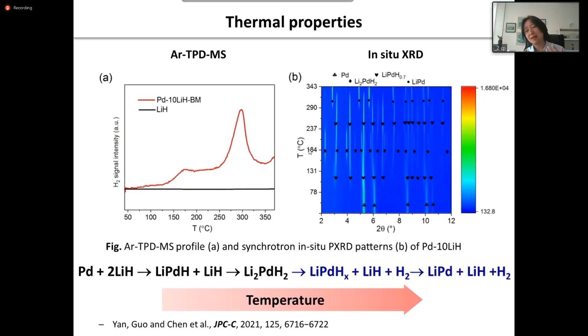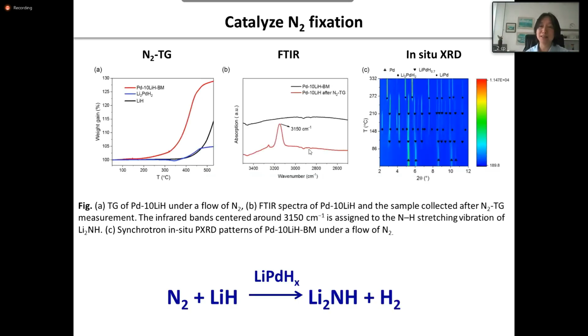So that means that this complex hydride can be facilely synthesized by heating palladium with lithium hydride. And this is the formation. However, under inert atmosphere, this Li2PdH2 decomposes to the interstitial hydride, then back to lithium palladium alloy up to 350 degrees Celsius. So in this heat treatment, it forms and decomposes. And I would like to show what this means for our research, especially for nitrogen fixation.